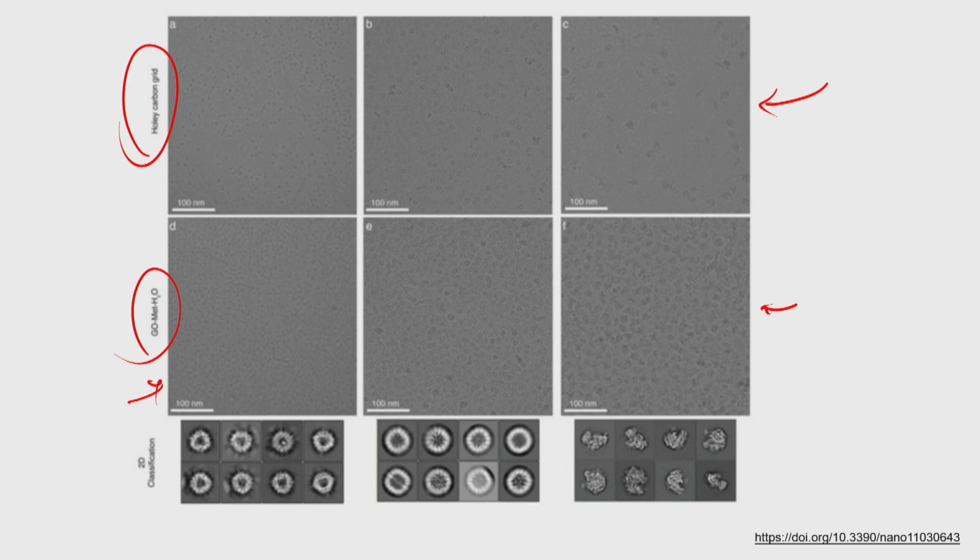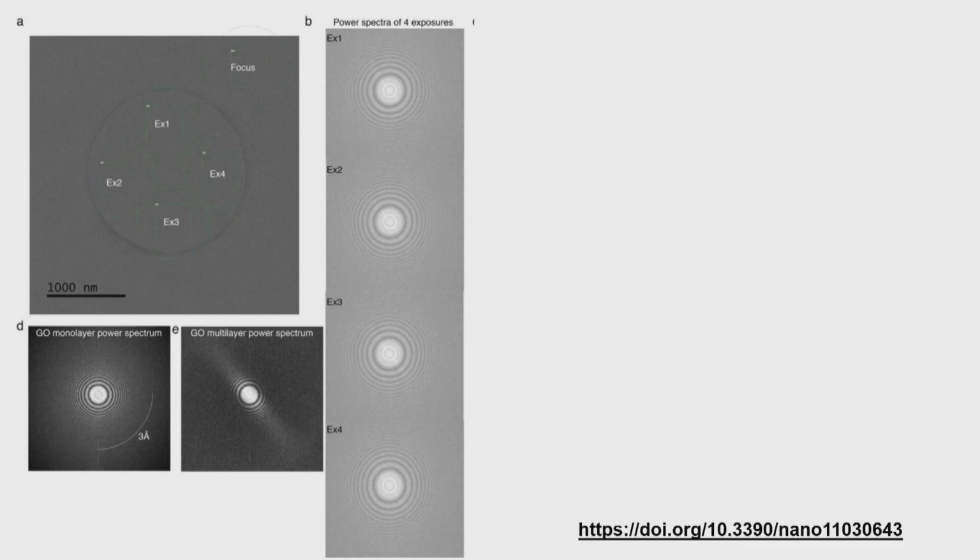Why is it absorbing more protein sample? Because there are some functional groups, and those are charged molecules that may attract more protein sample. One more thing, the graphene oxide grid has all these functional groups, the COOH group, epoxy group, OH group, that make these grids very hydrophilic, so it can absorb the protein sample easily, and we do not need to do glow discharge all the time whenever we are doing the imaging.